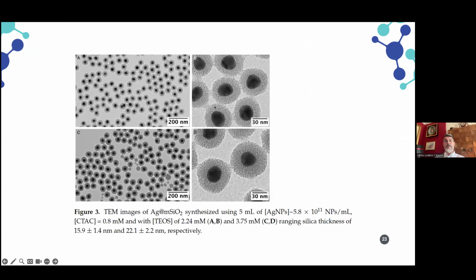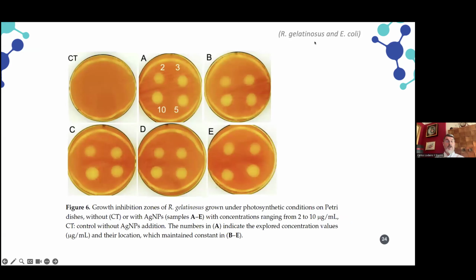In this case, I show you two pictures just to demonstrate the high monodispersity of the nanoparticles, and also the high monodispersity of the layer we can create around the nanoparticle. These layers are between 15 to 22 nanometers, depending on the methodology we use. This system was, for example, tested with water contaminated with a bacteria, Rubrivivax gelatinosus. This bacteria is a biomarker control for the quality of the water.